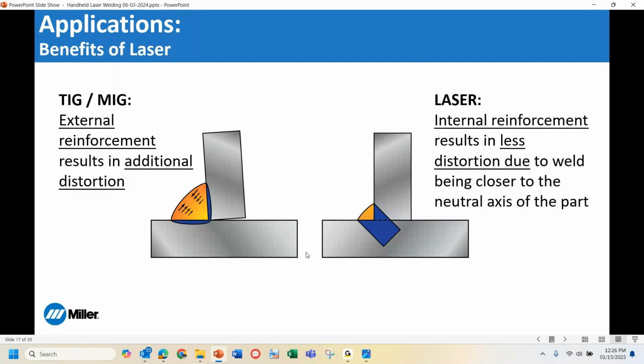So where do the benefits of laser really come from? Like I said, if you have a traditional TIG or MIG welding process and you have that external large leg size, for example, when steel solidifies, it shrinks about 10%. And that's where we get that distortion. You have a lot of torsion or torque as we move away from the neutral axis of the component. And when that weld solidifies, it causes that pulling effect, which causes the member to basically tip.